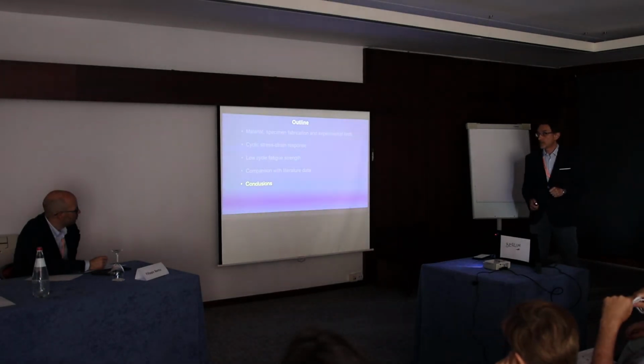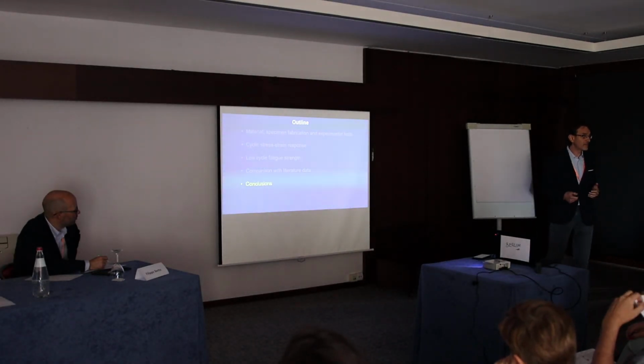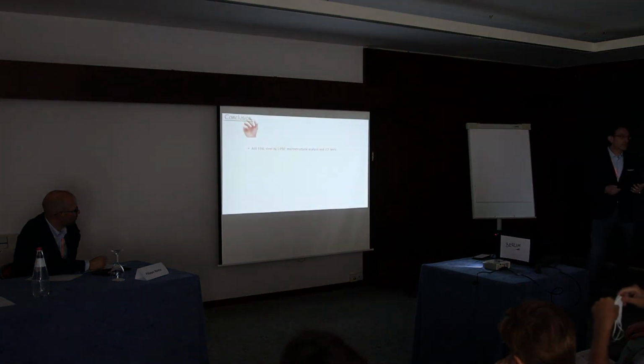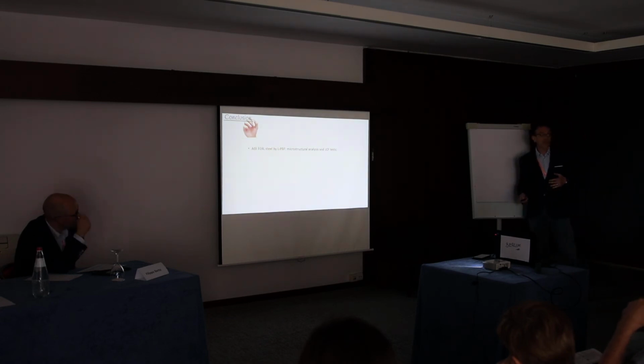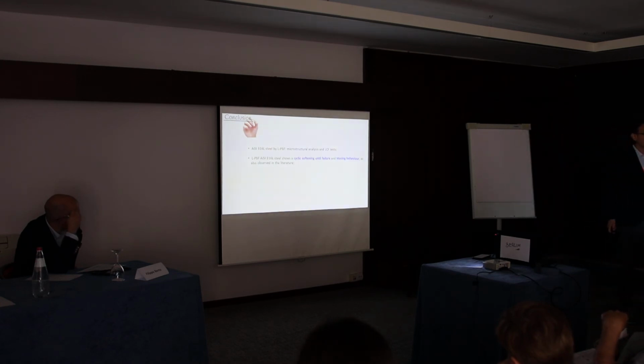So now I can conclude my talk by summarizing some main findings. I showed you some experimental tests concerning an additive manufactured 316 steel. I showed you some results concerning microstructural analysis and low-cycle fatigue tests. The results show that this type of additive manufactured steel shows a very pronounced cyclic softening until failure, and also shows a Masing behavior. And this behavior is also observed in other literature studies.